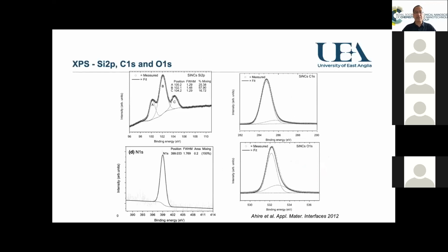Basically, after the synthesis, we needed to characterize the materials as well. For example, we use XPS to look at the surface of the materials we synthesized. Silicon is the main material, and then obviously we have oxygen, carbon, and if we have amine capping, we have nitrogen on the surface as well. So XPS is one typical method we could use to characterize the materials.